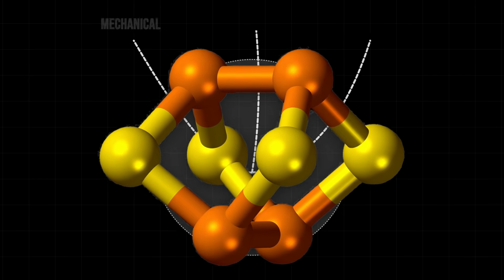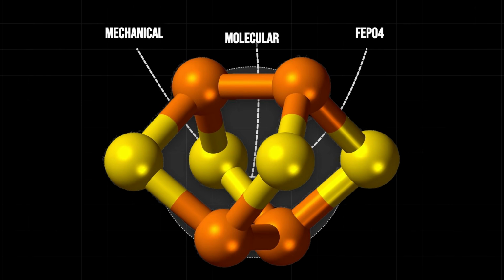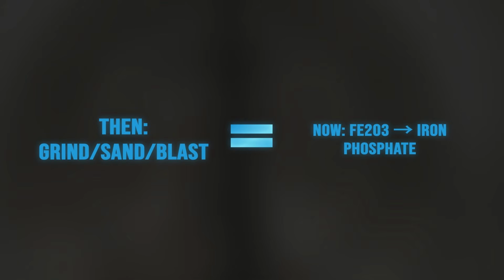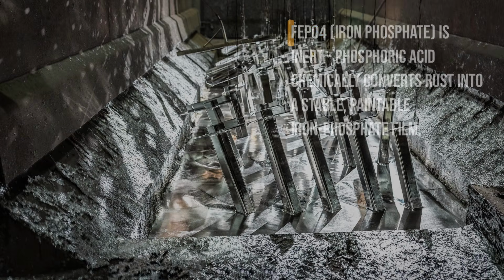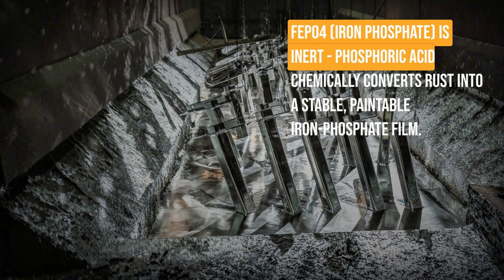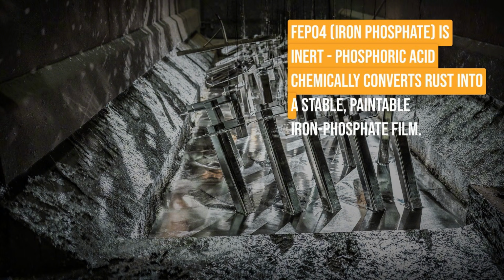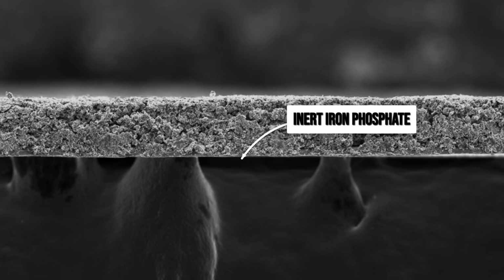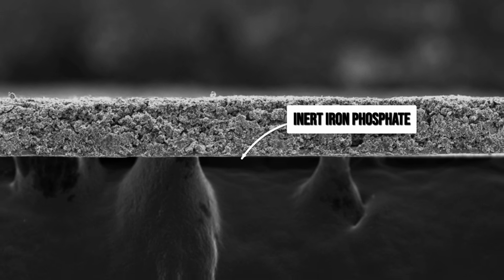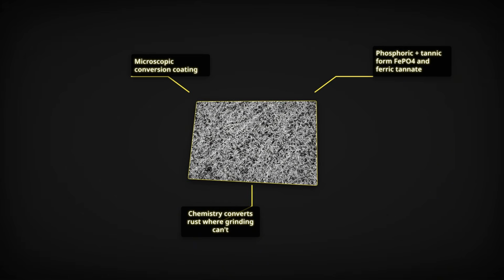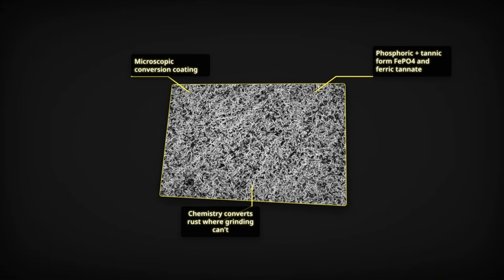Phosphoric acid works differently. When it contacts iron oxide, a chemical reaction begins at the molecular level. The acid converts Fe2O3 into iron phosphate. Iron phosphate, written as FePO4, is not reactive. It does not continue to oxidize. It bonds tightly to the base metal and forms a hard, inert layer. Under a microscope, it looks like a conversion coating, sealing every pore of the original rust surface from the inside out.